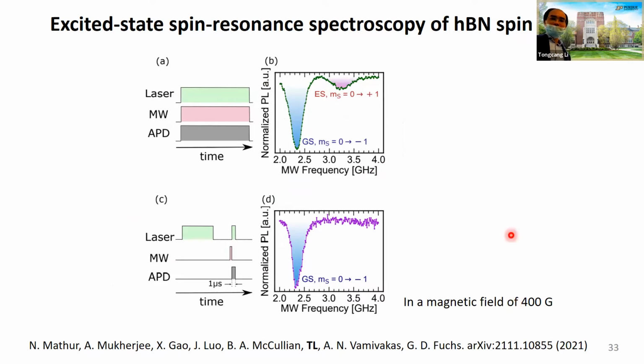In order to confirm this is really the excited state, we also performed laser excitation. One is CW laser excitation, where you observe both the ground state and the excited state. The other uses a pulsed one: you use the laser to initialize and then turn off the laser. Once you turn off the laser, the electron decays from the excited state to the ground state, so there is no more excited state. That's why we only observe one peak from the ground state and no peak from the excited state. So that confirms this is really the excited state.